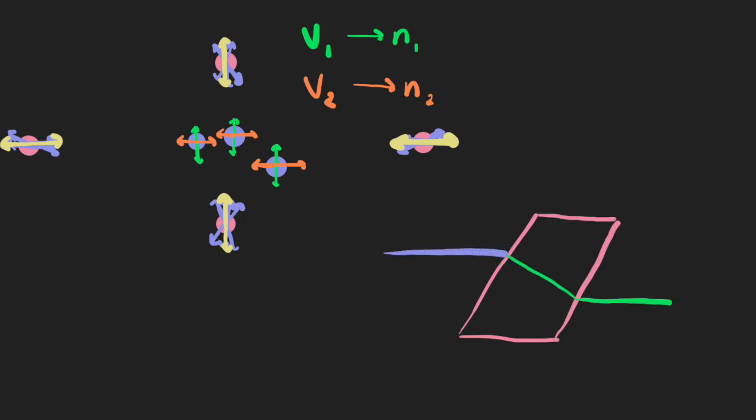Because the speed at which light travels through the crystal determines its index of refraction, we have a different index for each component. And so our unpolarized light beam traveling through gets refracted as two polarized light beams of equal power, each polarized perpendicular to the other. Crystals that behave this way are called birefringent.